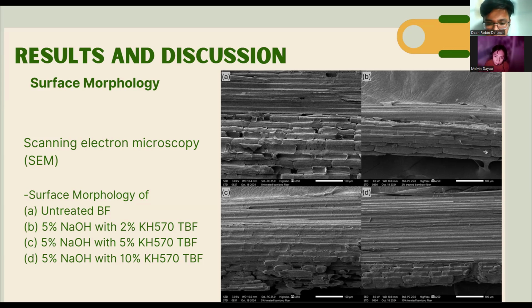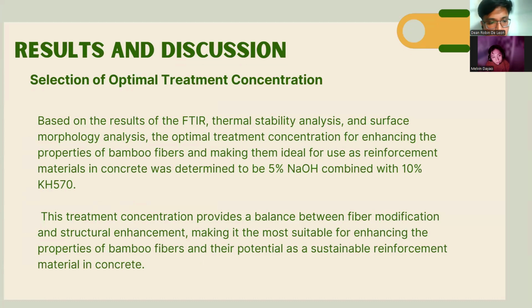for this chemical analysis. And based on the results of the FTIR, thermal stability analysis, and surface morphology analysis, the optimal treatment concentration for enhancing the properties of bamboo fibers and making them ideal for use as a reinforcement material in concrete was determined to be 5% NaOH combined with 10% KH570. This treatment concentration provides a balance between fiber modification and structural enhancement, making it the most suitable for enhancing the properties of bamboo fibers and their potential as a sustainable reinforcement material in concrete.